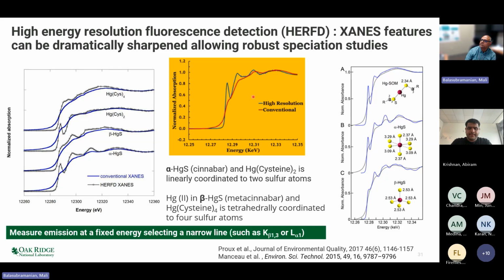For example, in the absence of high resolution fluorescence, you cannot differentiate any of these mercury compounds. But with high resolution fluorescence detection, you can say that alpha mercury sulfide and the corresponding cysteine compound have similar speciation, while this Hg cysteine 4 compound has a speciation more similar to beta HgS. So this is very powerful in understanding coordination symmetry and the local structure in these compounds. And it is used quite a bit in speciation studies.